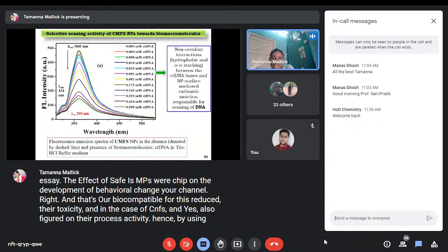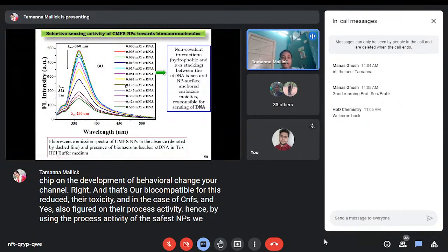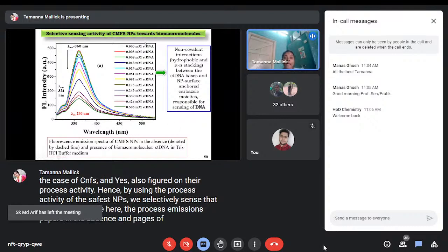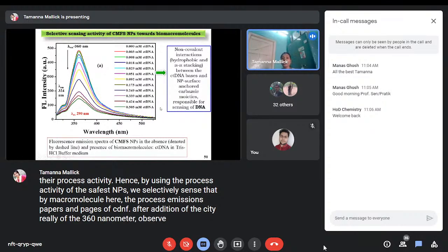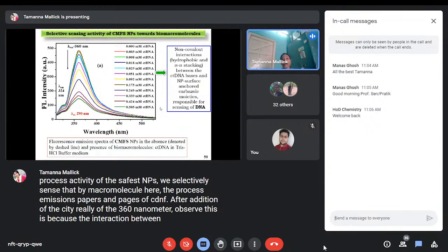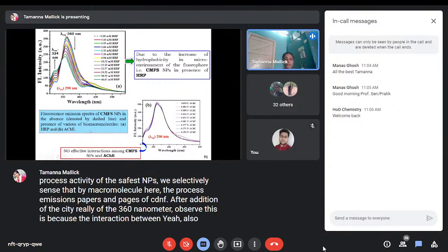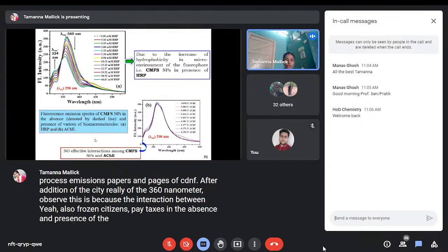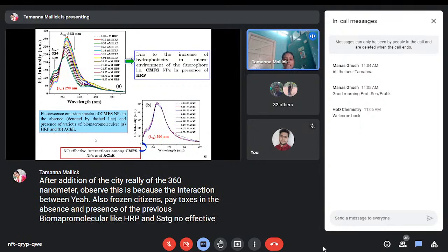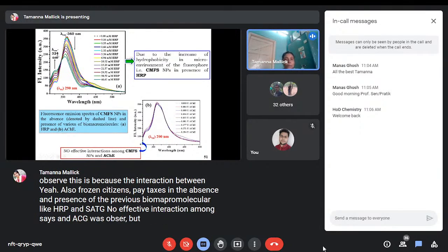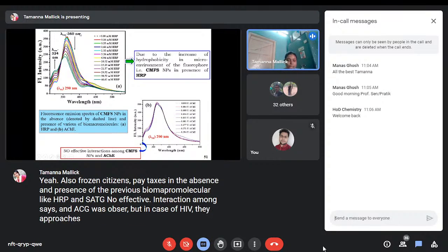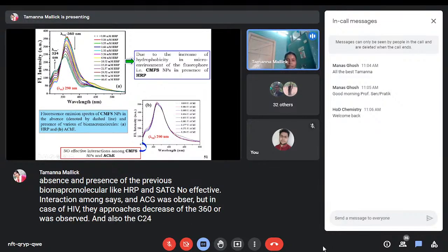Hence, by using the fluorescence activity of the CMFS NPs, we selectively sense the biomacromolecule. Here are the fluorescence emission spectra of CMFS NPs in the absence and presence of ctDNA. After addition of the ctDNA, a gradual quenching of the peak at 360 nanometer was observed. This is because of the non-covalent interaction between the ctDNA base pair and the nanoparticle surface carbazole moiety, responsible for this sensing. Here also are the fluorescence emission spectra of CMFS NPs in the absence and presence of various biomacromolecules like HRP and AChE. No effective interaction between CMFS NPs and AChE was observed, but in the case of HRP, there is a progressive decrease of the 360 nanometer peak, and also the 324 nanometer peak gradually increases.